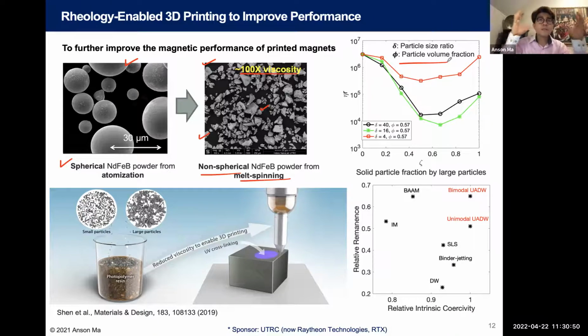Because you can think of this as kind of a space filling exercise, right? You have the big particles, but in between the big particles, you have tiny spaces. If you have smaller particles that will fit in that space, you can pack more, right? So by doing that, you can push up the particle volume fraction without jumping up the viscosity as much. So this is what we did.